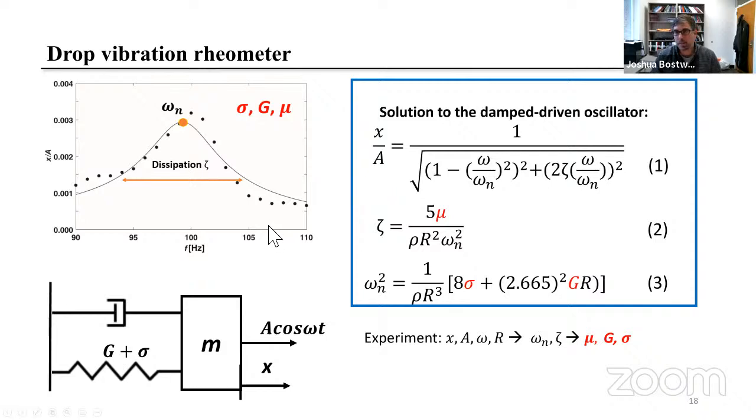That depends upon the natural frequency and the dissipation and the bandwidth in your system. So what we did is a lumped parameter model, if you think about it from the control systems aspect, where we took the natural frequency omega n from this control systems perspective, and we put in the physics of surface tension and the physics of shear modulus.